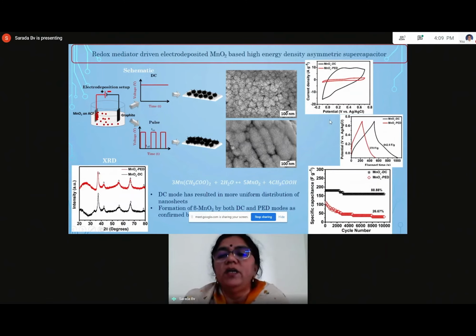You can see over here that by using direct current deposition, it has given much better cyclic voltammetric performance, and also the specific capacitance obtained is very stable for 10,000 cycles. It has retained 88%, and also the specific capacitance is very high.